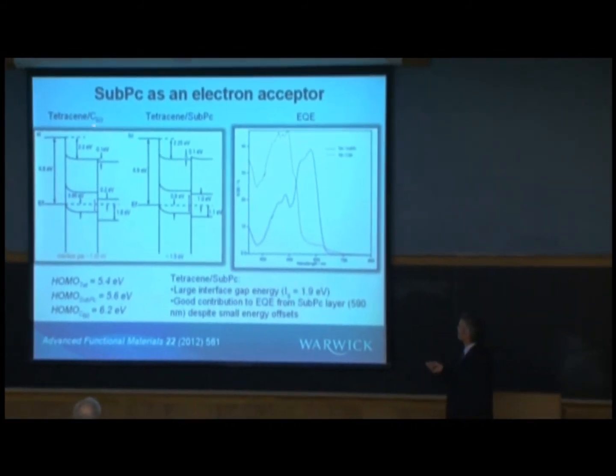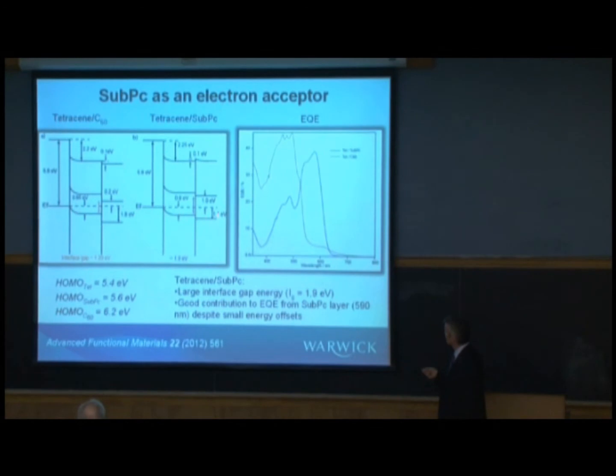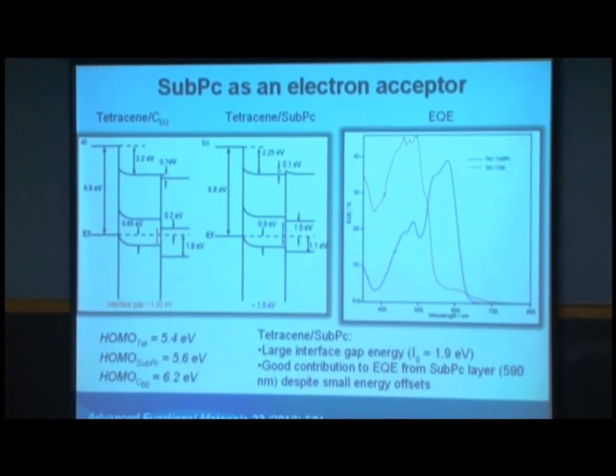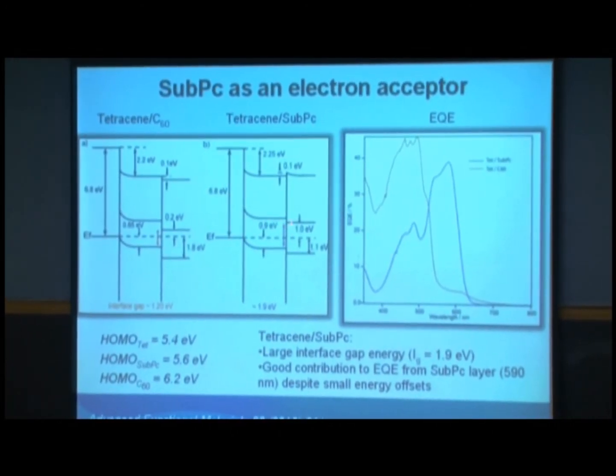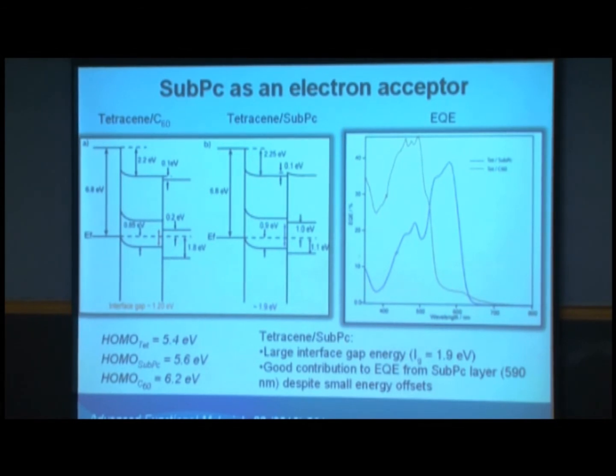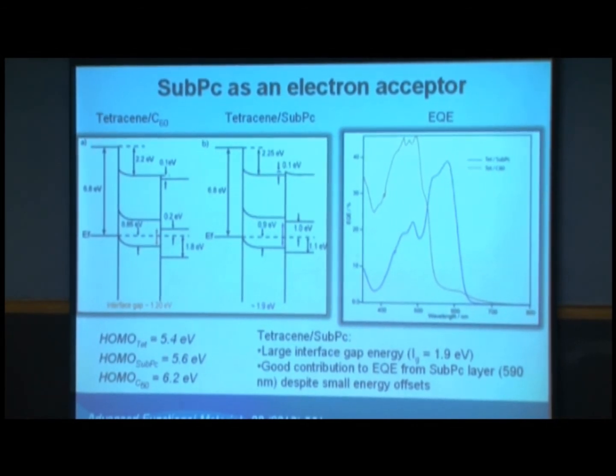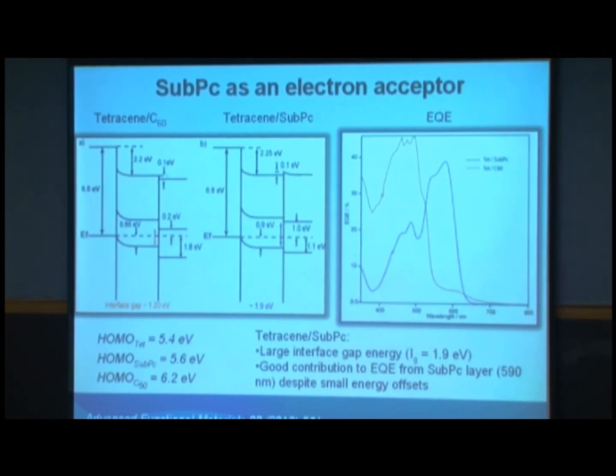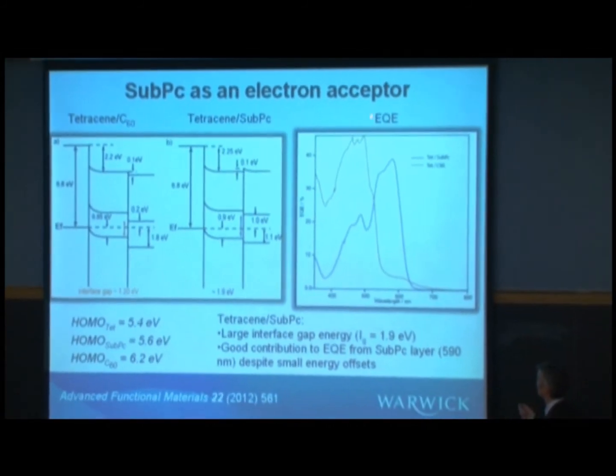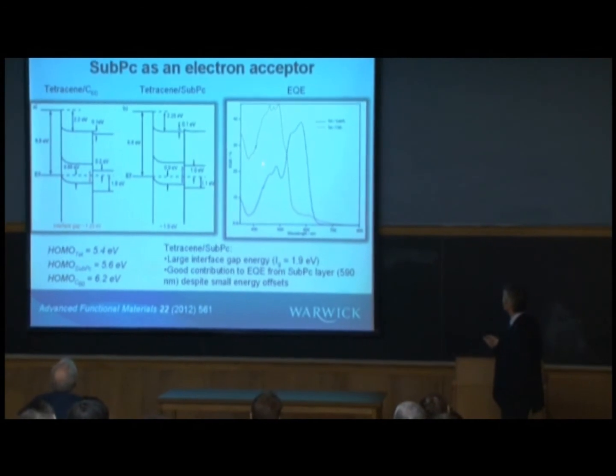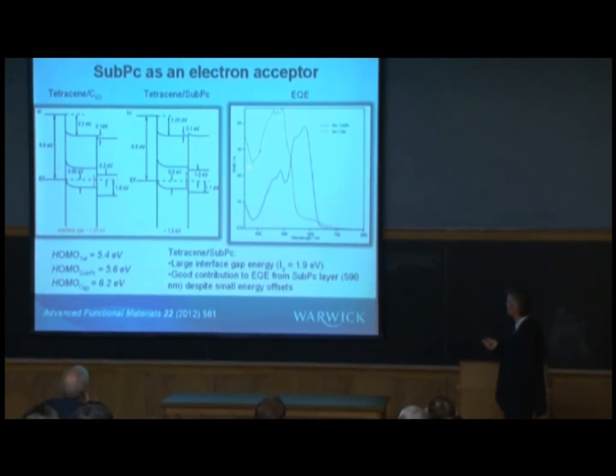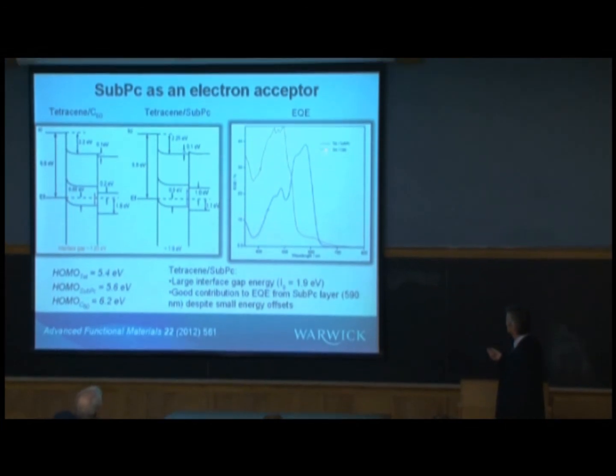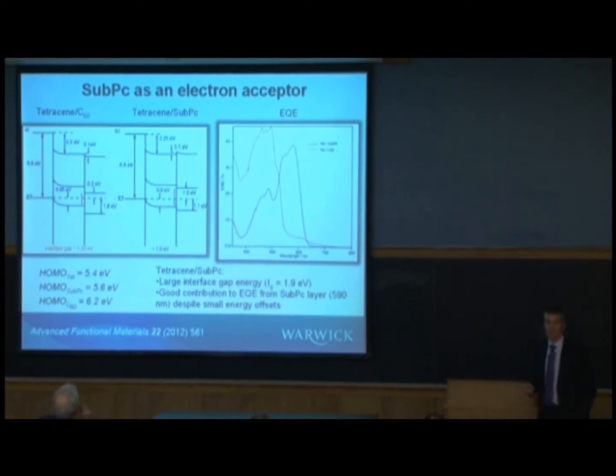So what we decided to do is replace the C60 with subphthalocyanine, because if you look at the energetics, we get a very large interface gap energy now of 1.9 electron volts, and the offsets are much lower, but should still be large enough to induce the dissociation, which should then hopefully give a larger voltage. And this is just proof that both materials are contributing to the photocurrent. These are external quantum efficiency measurements for a tetracene C60 device here. This is the tetracene absorption, and the tetracene subphthalocyanine device. So this is the tetracene absorption, and this is the subphthalocyanine absorption.